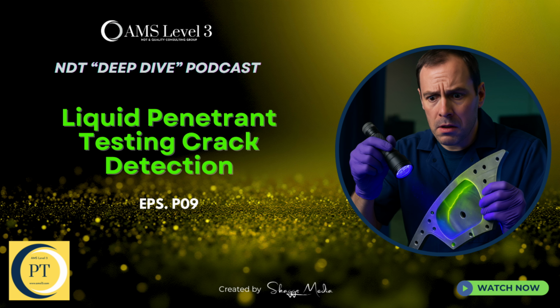The downside is the penetrant in the flaw is also emulsifiable. So if you overwash, you get it out of the crack. Precisely. So you have very strict controls. Water pressure can't exceed 50 psi. That's like gentle garden hose pressure. Definitely not a pressure washer. And the water temperature needs to be controlled too, usually between 50 and 100 degrees Fahrenheit. Careful control to protect that trapped penetrant.